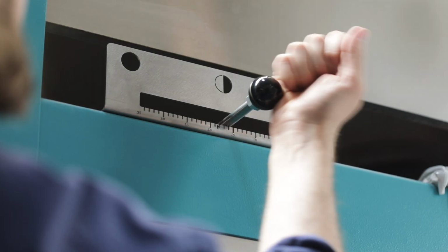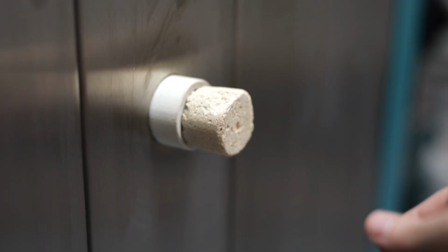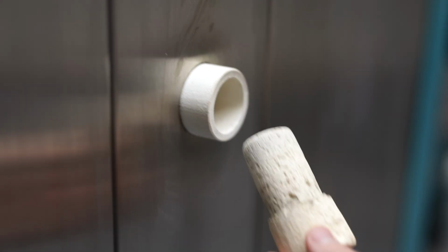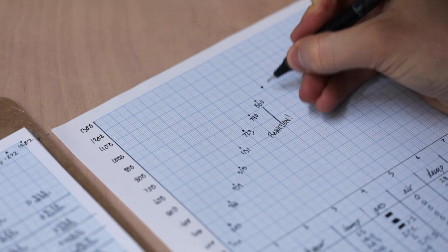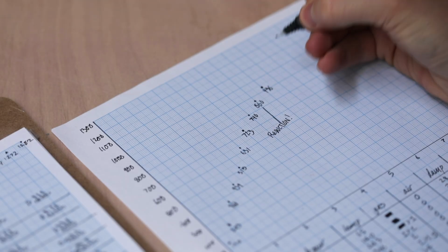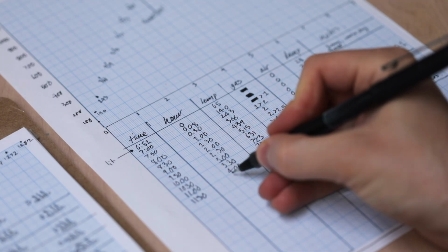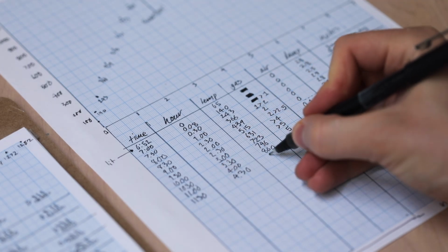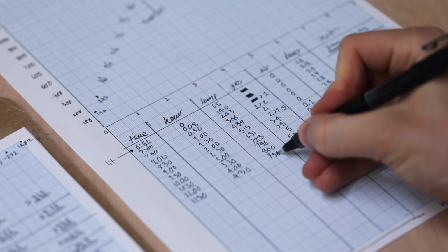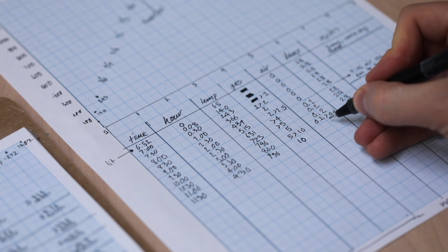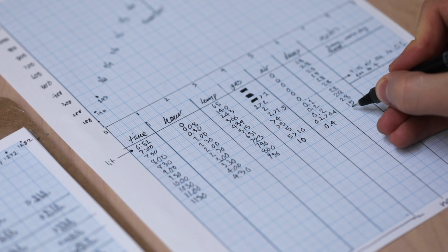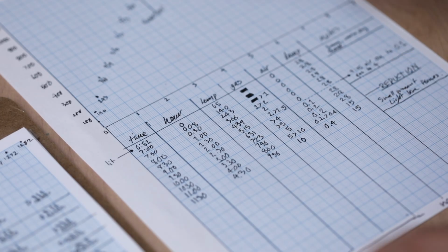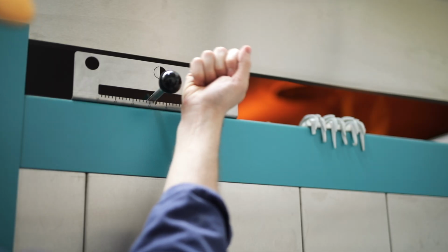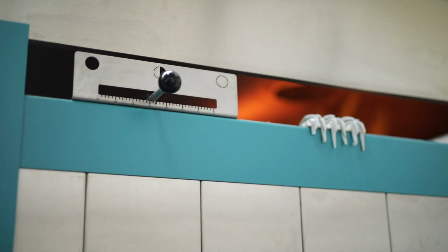Then, at 860 degrees exactly, I initiate reduction, which I do by increasing both the gas and air pressure quite considerably, and at the same time I slide a damper over the flues of the kiln, which means the exhaust can't escape quite so quickly. This causes the fuel inside the chamber to burn inefficiently, as there's simply not enough oxygen, and the byproduct of this is that the burning fuel seeks oxygen from inside the clay and the glazes, thus changing their colours into something that's very difficult to replicate in an electric kiln.